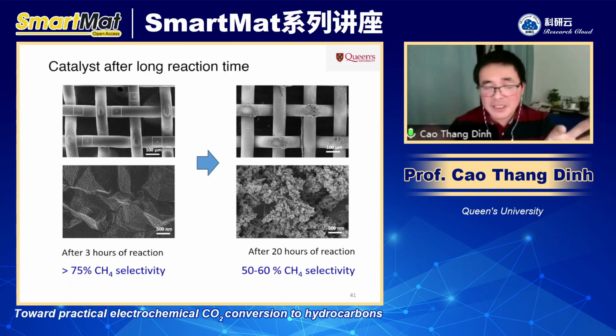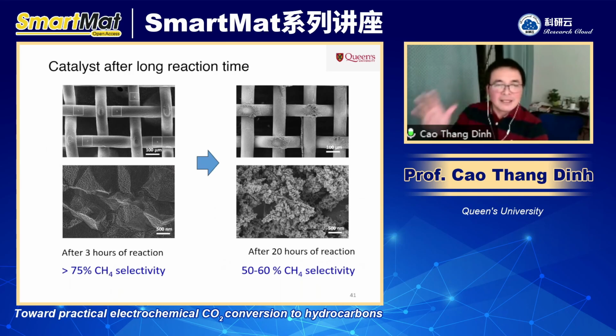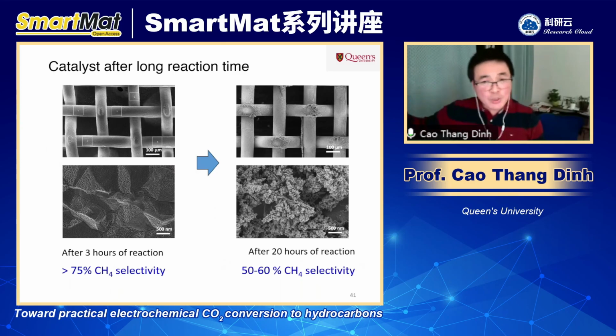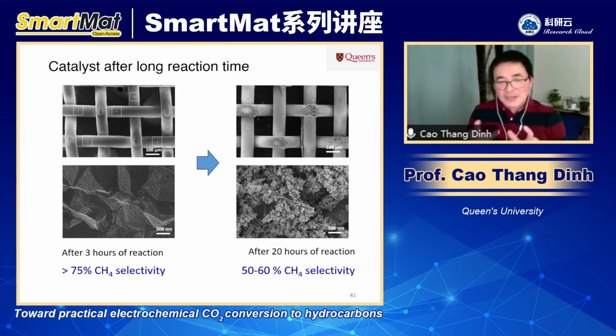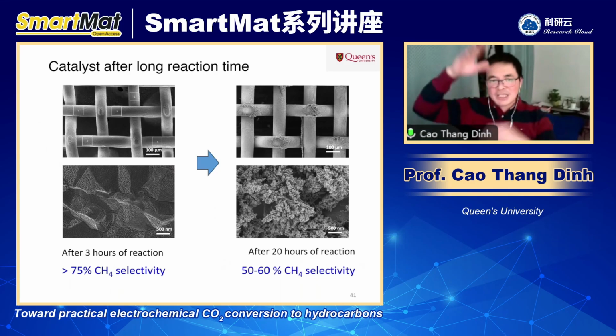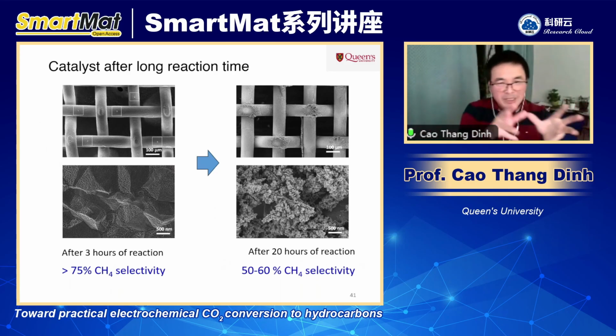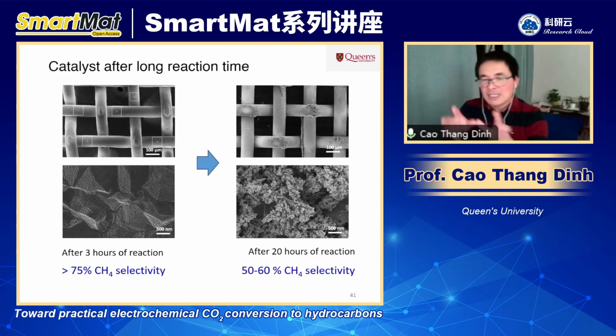And if you look at the surface of the substrate, you see a clear difference, right? On the left-hand side is the surface to make the methane. On the right-hand side, it started making ethylene. Wow. So methane goes down, ethylene goes up. It's increased the porosity of the substrate. So that means when you constantly apply the current, the surface of the copper keeps changing, increasing in terms of the porosity here. And the higher porosity of the substrate, the more likely we increase the formation of the ethylene.